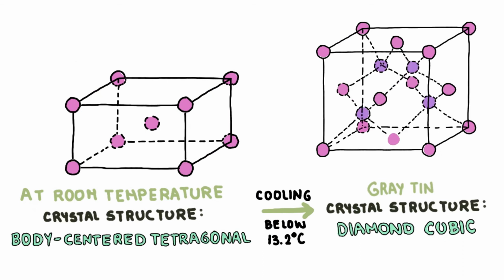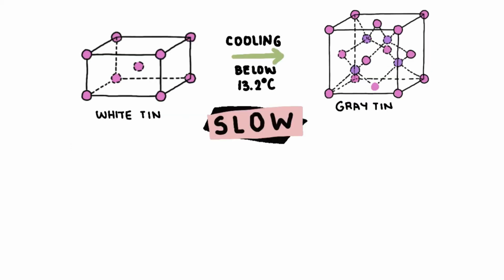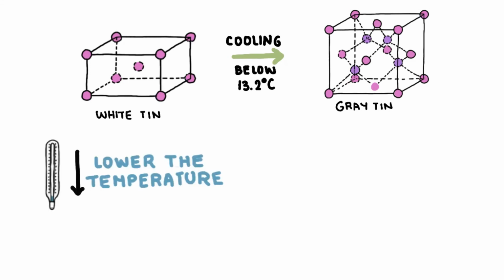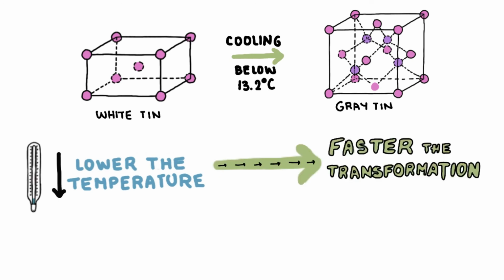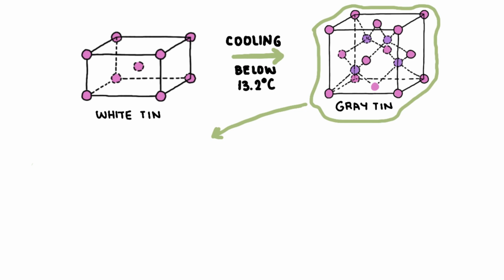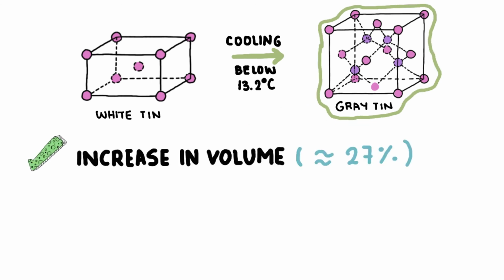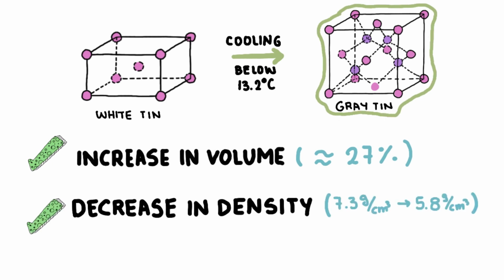It transforms below 13.2 degrees Celsius to gray tin, which has a diamond cubic crystal structure. The rate at which this takes place is extremely slow. However, the lower the temperature below those 13.2 degrees Celsius, the faster the transformation rate. Accompanying this white to gray tin transformation is an increase in volume, around 27%, and accordingly a decrease in density, from 7.3 grams per cubic centimeter to 5.8 grams per cubic centimeter.